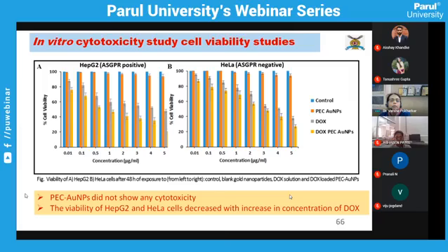The in vitro cytotoxicity studies were done in two types of cell lines, HepG2, which are known to be ASGPR positive, and the HeLa cell line, which is ASGPR negative. Because we wanted to establish the mechanism, that is the reason we went for these two types of cell lines, one which is ASGPR positive and the other which is ASGPR negative. The pectin reduced gold nanoparticles did not show any toxicity here. A concentration dependent decrease in cell viability was observed, and the viability of HepG2 as well as the HeLa cell line both decreased with the increase in DOX concentration.